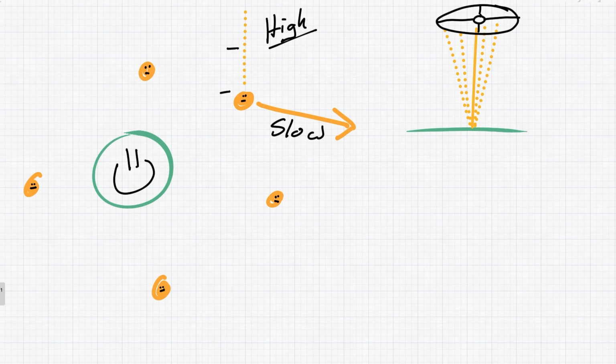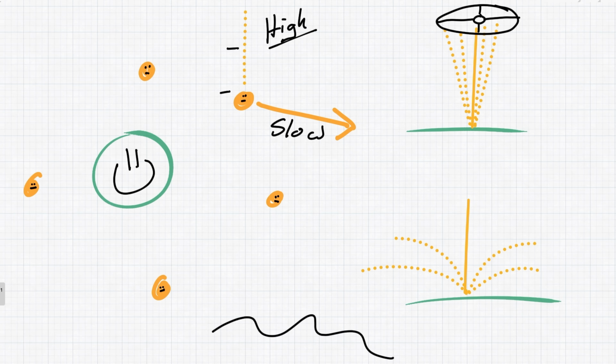And what this looks like at a macroscopic level, again, if we have our sample and the electron beam hitting it perpendicularly, these secondary electrons are just ejected in any which way. They also tend to be affected by the topology of the sample a lot. So if you've got a beam coming in and it hits an angled surface, a lot of those secondary electrons will be emitted as you'd expect from the side of the sample.